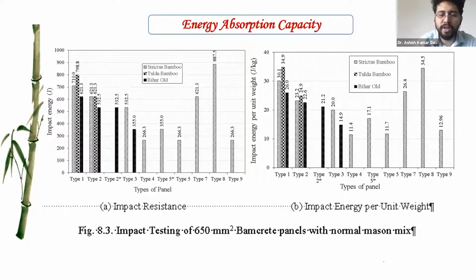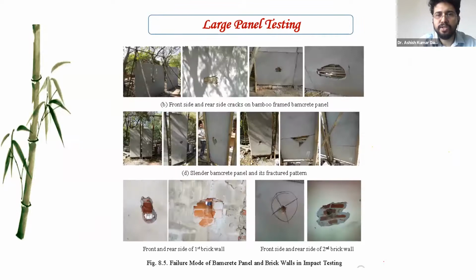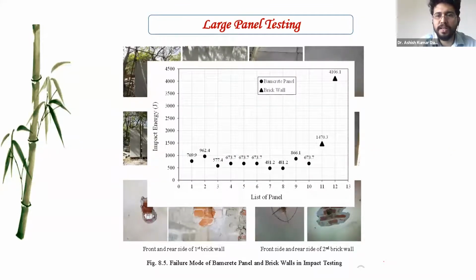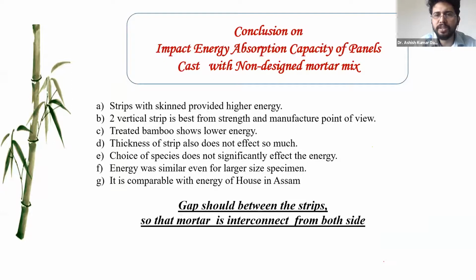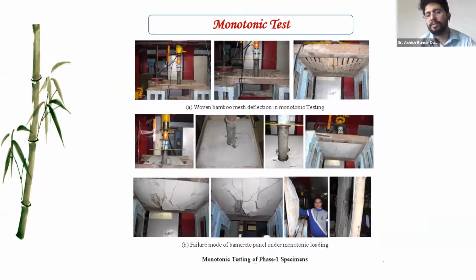So it signifies that the traditional process of concrete panel casting in Assam type houses follows the normal mason mix mortar. You can see this is the horizontal impact testing also conducted, and we found the level of strength is quite similar to whatever we found in the case studies of the 40 year old houses. So it is concluded that they have been using this normal mason mix. After that, we started work on design mix.